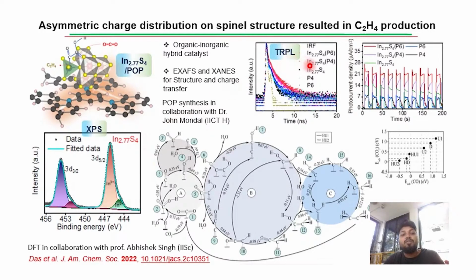From TRPL, we proved that in this kind of composite system, the electron has been stabilized in the conduction band for more time, and we are getting more lifetime, which was reflected from the improved photocurrent generation in the composite material. Here also we have proved from theory that the composite material can activate the CO2 in a much better way compared to the normal or pristine In2.77S4. Therefore, the improved activity has been obtained.